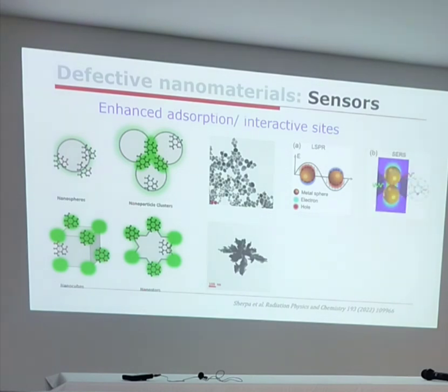So I can give you maybe one example up here. What you can see is, in this case, this particular species has been illuminated with swift heavy ion radiation so that the dendritic assemblies are formed. And you can see earlier there was no scattering that you were able to see, and now it begins to give this blue curve. That is because you are changing the morphology of the structure by introducing defects into the system.